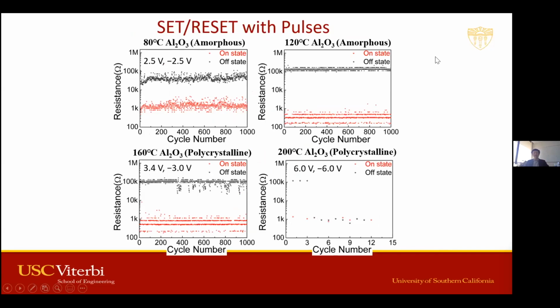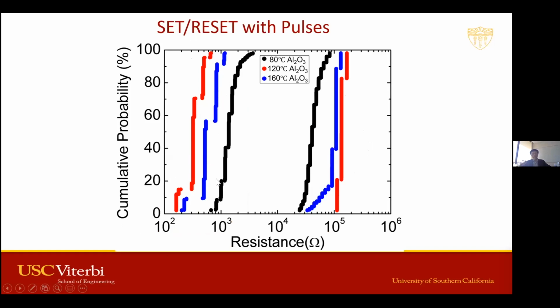Now let's look at using those devices as a memory device. You use a pulse at a relatively high voltage to switch on and off, then a pulse at a relatively low voltage to measure the conductance. Here we use pulses to switch those devices on and off, and you can see they behave very differently. If we look closer, this 120 degrees C device seems to perform the best as a memory device. Best means it has the largest on-off ratio, and the spread of the resistance in both on and off states is narrower. Here are the statistics: the 120 degrees C device, the red one, has the best performance.